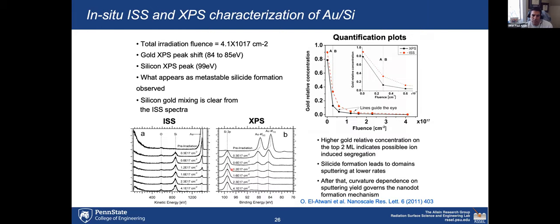And so we did a number of studies using a combination of the ion scattering spectroscopy that I shared with you earlier and X-ray photoelectron spectroscopy. And we found that there was a unique transition influence of irradiation combined with the amount of metal on the surface. To remind you, the metal films that we deposited were about 10 nanometers, very thin films. And as we irradiated, there were no patterns formed. It wasn't until we reached ion-induced mixing and eventually about 2%, 5% of the metal that we were able to reach patterning. And we confirmed this with in situ GISAXS studies that we conducted at Brookhaven.